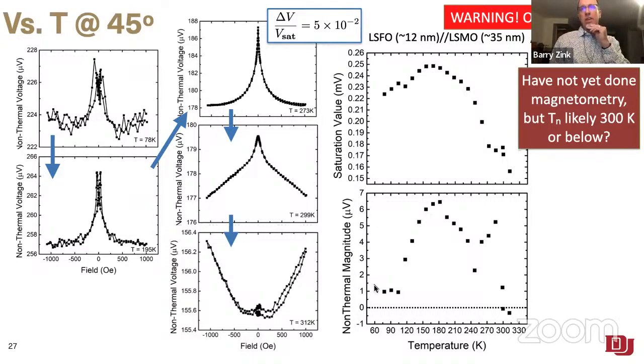And you can see that, again, we have a sort of complicated temperature dependence, where the lowest signal sizes we're seeing are somewhat above 300 Kelvin. Below that, we see much larger changes in the resistance signal that we're measuring. And again, the question is, how does that correlate with the different magnetization and Néel vectors that we expect to be manifested in the sample?